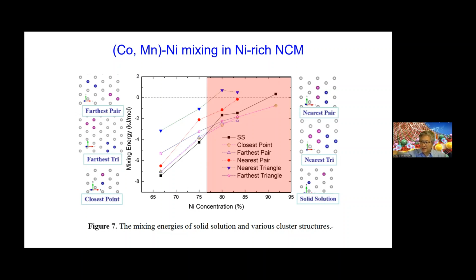They are minority species, but not just minority randomly distributed; they precipitate, so that effectively the overall material behaves like a phase-separated material with lithium nickel oxide. So with an abrupt change at more than 75% nickel concentration, the material rapidly behaves like pure lithium nickel oxide. That is the source of a lot of challenges and material property evolution.